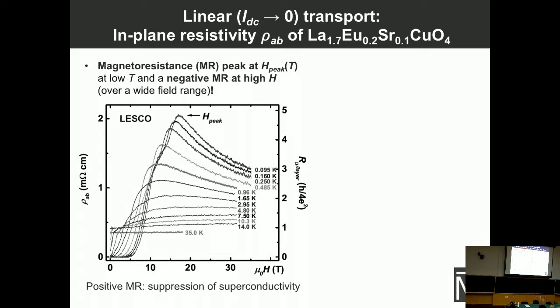same for both materials. What we see at high temperatures is flat, it doesn't really depend on the magnetic field, and then as you reduce the temperature, you start seeing positive magnetoresistance, which means that you're suppressing superconductivity. But as we lower the temperature further, this broad peak becomes sharper, and it's followed by a wide range of fields where one observes a negative magnetoresistance. This is actually very surprising because it has not been seen in cuprates.